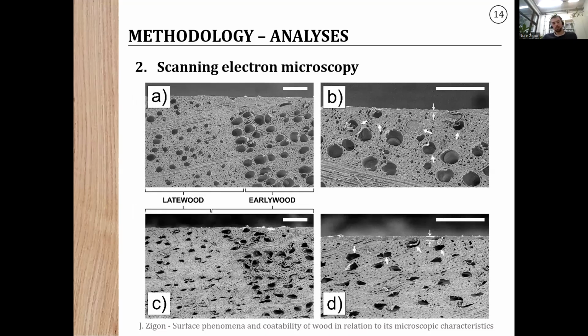2 examples using scanning electron microscopy for determination of the coating thickness on either normal wood above and densified wood below. Besides that, after the densification, the structure of wood is completely, let's say, different than before. Also, the coating penetrated less into the surface because of the denser substrate. Let's say it simply.